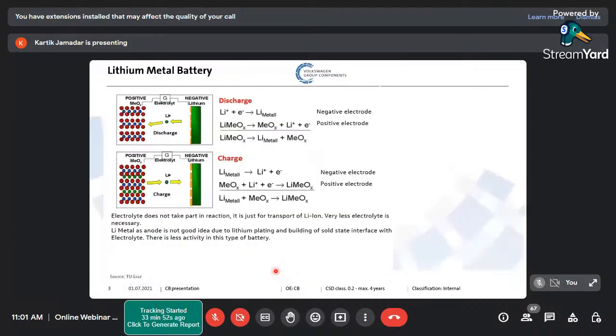And then came the solution. Why not have something like a metal oxide which is holding the oxygen? The lithium occupies the space within the metal oxide, and the metal oxide is such that you have transition metals, and these metals take up a different oxidation state and can accommodate the incoming lithium. At the same time, when lithium wants to go away, this metal oxide can take a different oxidation number and release the lithium. So you can see here, when you are discharging, the metal oxide is releasing lithium and coming into a different oxidation number.